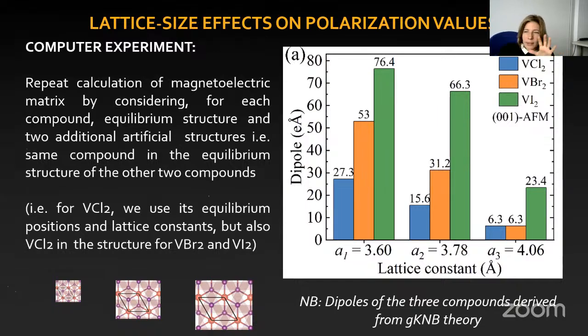So we try to disentangle, let's say, the chemical effect, by having larger atomic spin-orbit coupling in iodine and chloride, compared with the structural effect. So having the ions closer and different hybridization channels. And the effect that actually arises from changing the lattice constant is pretty strong.